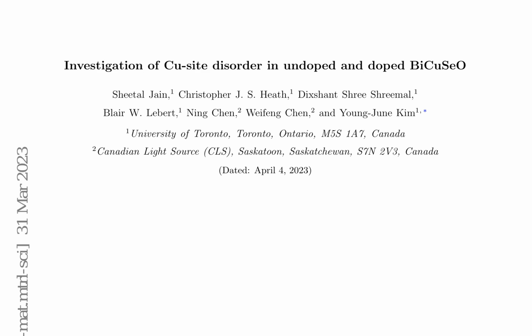The experimental results section of the research paper presents X-ray diffraction, XRD, data for undoped BiCuSeO and its doped variants at room temperature and as a function of temperature. At room temperature, the XRD data was fitted using Rietveld refinement to extract the lattice constants of the tetragonal unit cell. The lattice constants obtained from this fitting are tabulated in Table I. It is observed that the lattice constants show almost no change with Ag doping within the error bar. However, in the case of Pb, Ag dual doping, the lattice constants exhibit a more pronounced increase with doping, particularly the lattice constant c. Isotropic mean square displacements, Uiso, were also obtained for each atom from the Rietveld refinement of XRD